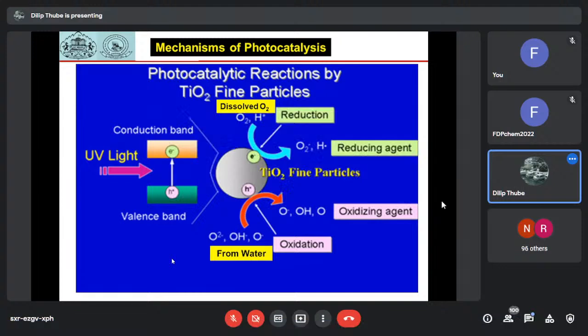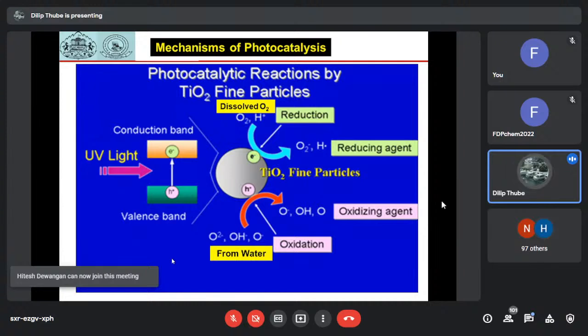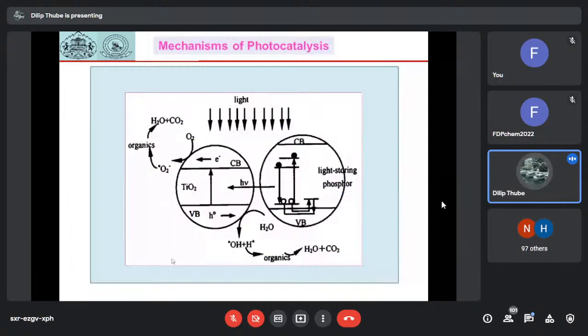If you look at the TiO2 material, nascent TiO2 material, as the band gap is there and the rate of electron hole recombination is more, the electrons are not made available for the reduction as well as oxidation. Therefore, minimizing electron hole recombination rate of this TiO2 photocatalyst is the most important challenge, and this challenge can be met by modifying the TiO2 materials by converting it into nanocomposite material.